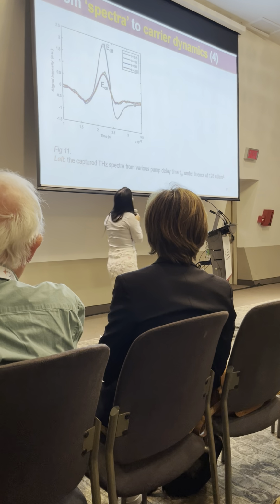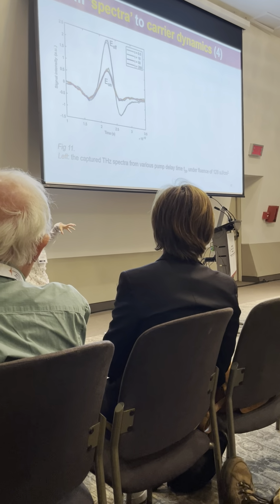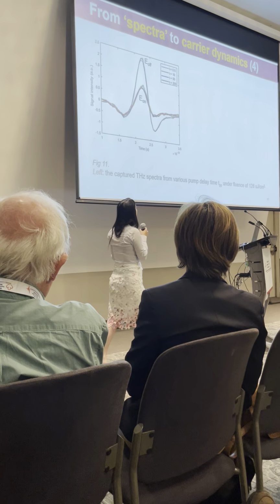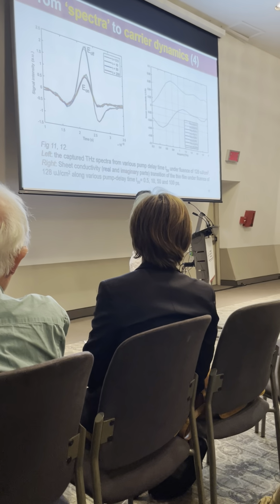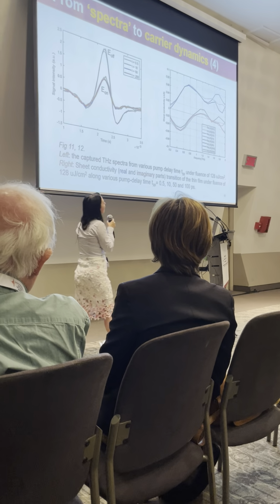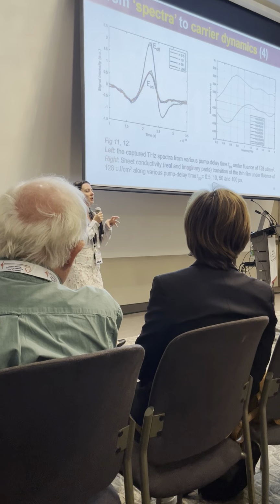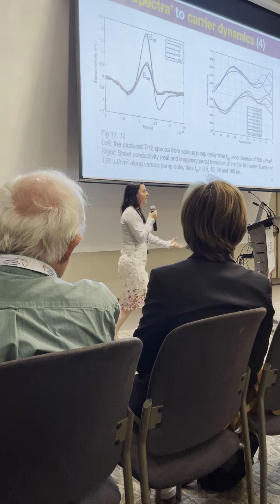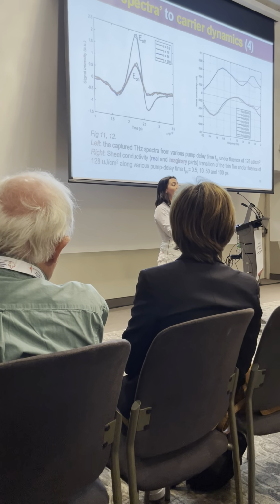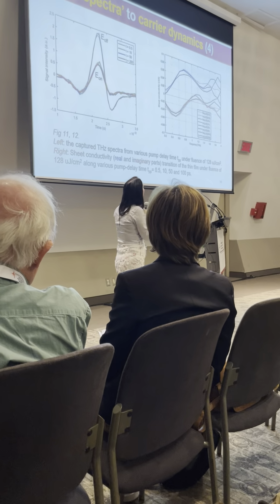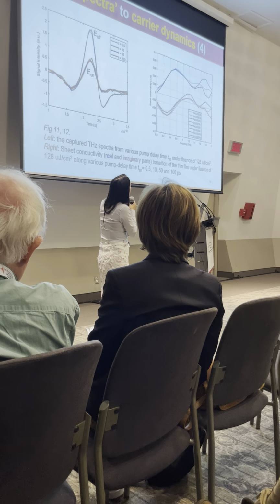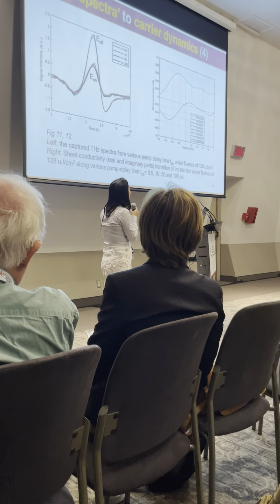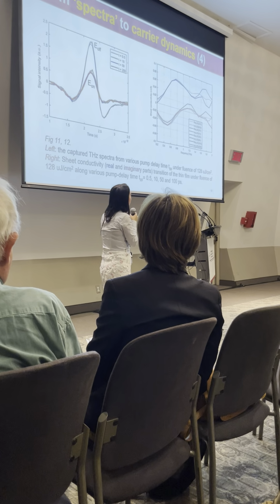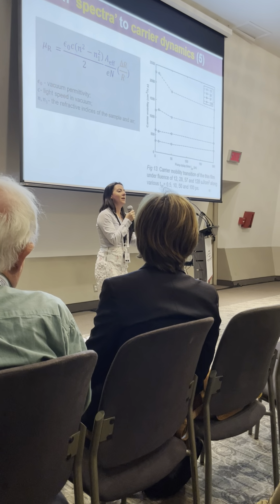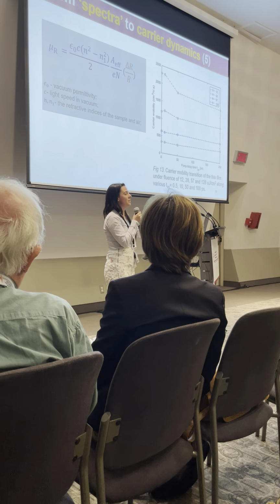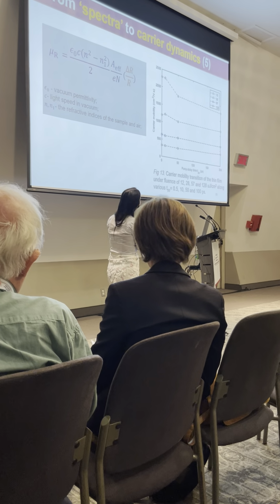The next step for us in our group is to look in more detail at the waveforms that we collected and the spectral data, so the difference due to photoinduced. And we have calculated what the sheet conductivity should be. Now, because this was a thin film, we were expecting to see a lovely Drude response, but you can clearly see that we have something that looks a little bit like a Lorentzian shape here. So the next step for us will be fitting this with the Drude-Smith model. We think we're having backscattering due to some of that polycrystallinity of thin films.